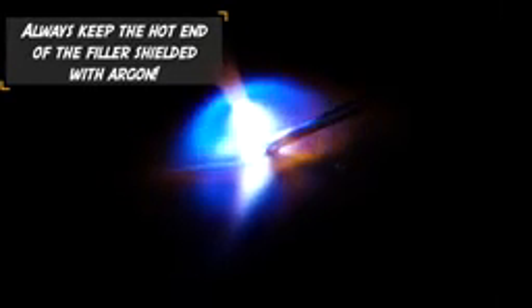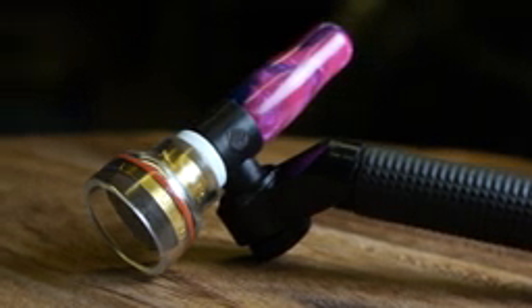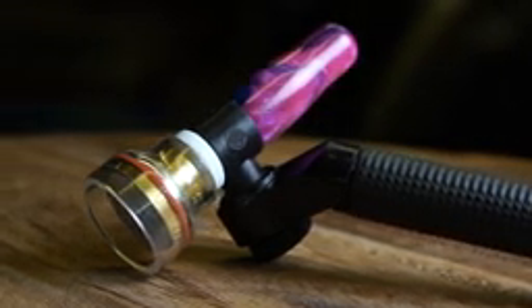For a seamless clean tie-in, start on your last ripple and increase amperage until your toe width of the weld matches the previous weld's toe width, and then move forward one ripple and then start adding filler rod. Use 1 millimeter or .035 or .045 filler on .065 or 1.6 millimeter wall tube. Bigger filler requires more amperage to melt, which equates to more heat input. Set your machine to 10 amps over what you would normally weld with. Travel speed varies per person, but make sure you are in control of the puddle.